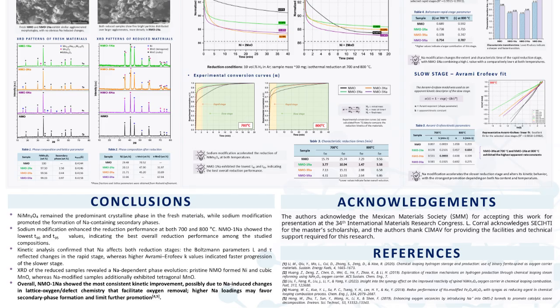Kinetic analysis showed that sodium affects both stages of the reduction process. The Boltzmann analysis revealed changes in the extent and characteristic time of the initial rapid stage, while the Avrami-Erofeev analysis showed an increase in the apparent rate of the slower stage. In addition, X-ray diffraction of the reduced samples revealed a sodium-dependent phase evolution. Pristine NMO formed metallic nickel and cubic manganese oxide, whereas the sodium-modified materials additionally exhibited tetragonal manganese oxide.